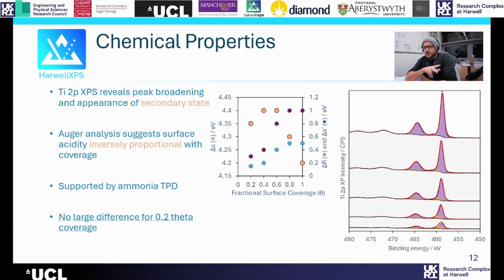If you're a bit confused as to what I'm talking about here, we do have an in-depth explainer video on Auger energies and initial and final states and all the maths that goes on in there. I will stick a link in the description below, but effectively this tells us a bit of information about the surface acidity of our tiny titanium sites, and that these are decreasing with coverage. The ammonia TPD analysis that we did to support this observation did trend in the same way. We see that our low loading catalyst did report a slightly higher acid site strength for this material, so this is a potential source for our increased activity.